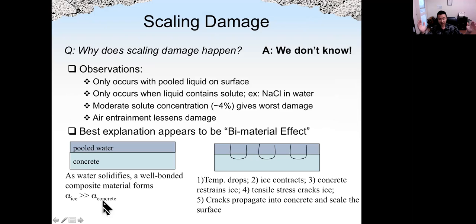So that means when temperature drops, the shrinkage of the ice layer will be much more compared with the shrinkage of concrete. However, we have very good bond between the ice layer and the concrete layer. So when temperature drops, ice will contract more than the concrete. So the concrete will restrain ice from further shrinkage, and that will generate tensile stress in the ice. So the ice will crack due to this tensile stress.